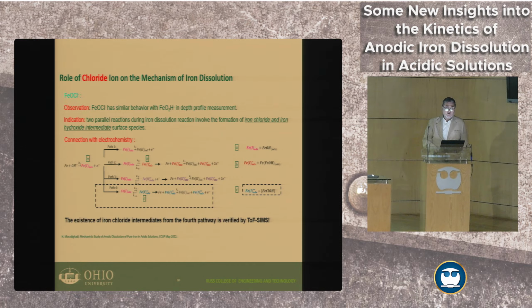So we have, in this part of the study, proven explicitly that this alternative pathway for iron dissolution, the chloride pathway, is actually true. Maybe we don't have every detail, right? We don't know exactly which chloride complex it is. Is it Fe something something chloride something something? We don't know that because we don't have an analytical technique to tell us exactly what the compound is on the surface, but we know that it has to contain chloride, and it's a compound because we got it by bombing the surface with ions and exploding it and detecting it.